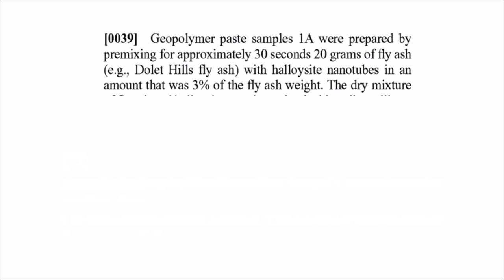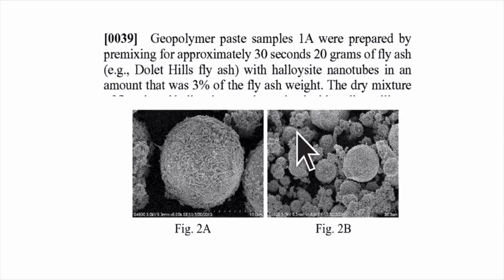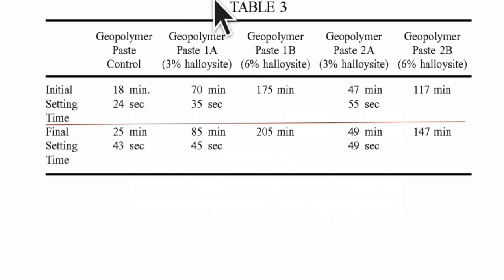What it is about: they take geopolymer paste samples, prepared by premixing for approximately 30 seconds 20 grams of fly ash with halloysite nanotubes in an amount that was 3% of the fly ash weight. That is, they have the fly ash spheres that are covered with a very tiny coating of halloysite. Result: geopolymer paste control, setting time 18 minutes, final setting 25. With 3% halloysite, instead of 18 minutes, 70 minutes setting time. Wonderful.